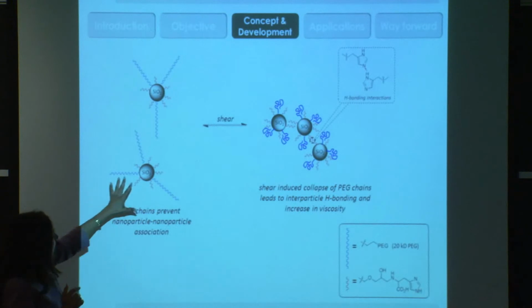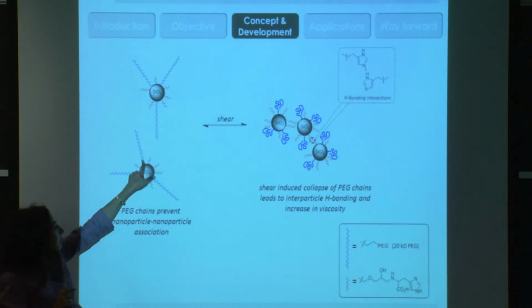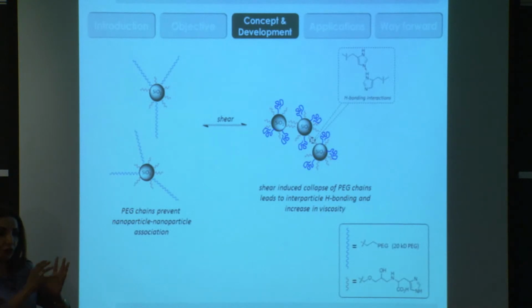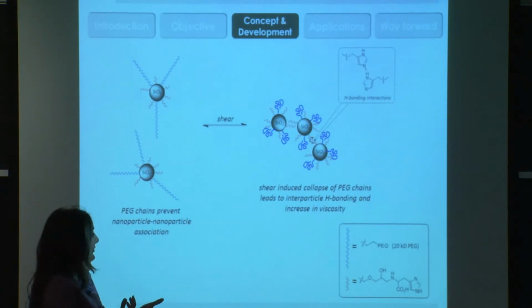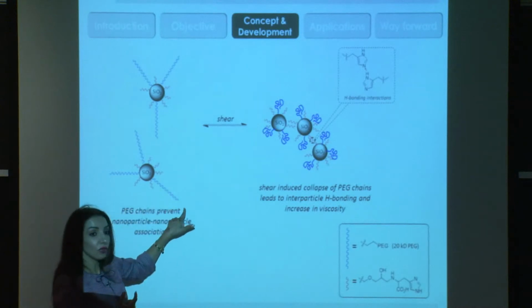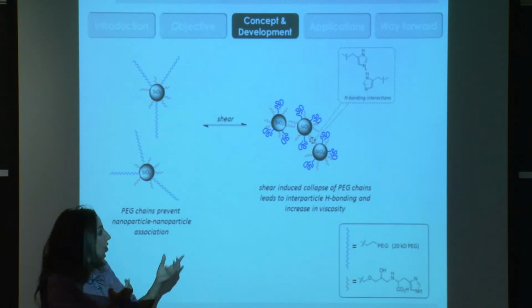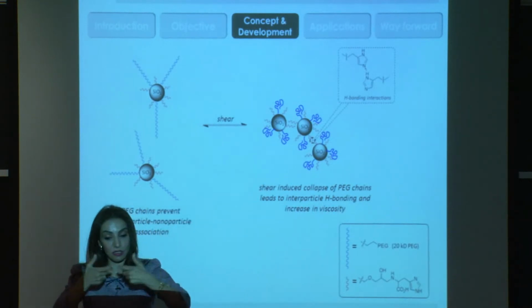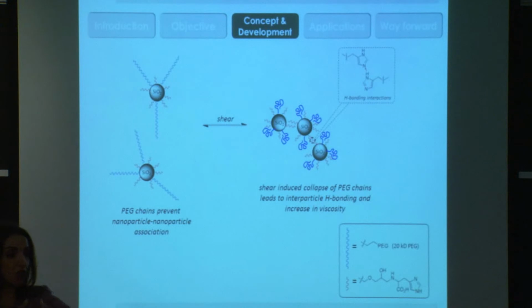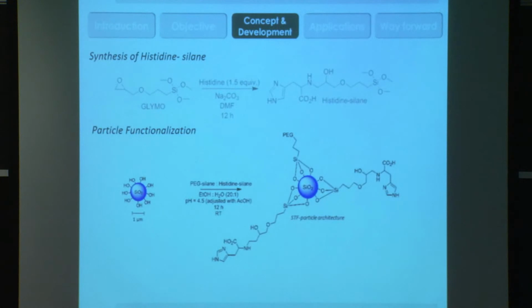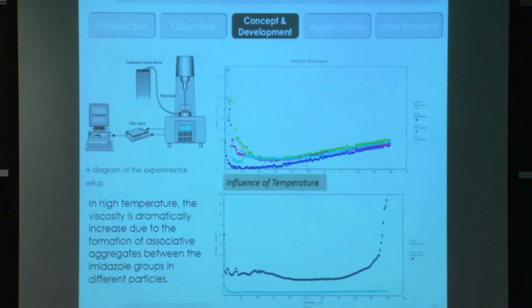So in normal state, this long chain will form like a shield for the histidine group. But when we apply any shear stress, this long chain will aggregate, making like a window for the histidine group in the short chain, and the histidine groups will start to connect with each other. So when you remove the shear stress, the long chain will relax again and cover the histidine group. So this is the mechanism of how this reversible process works. This is the synthesis in detail. I will not go through it.